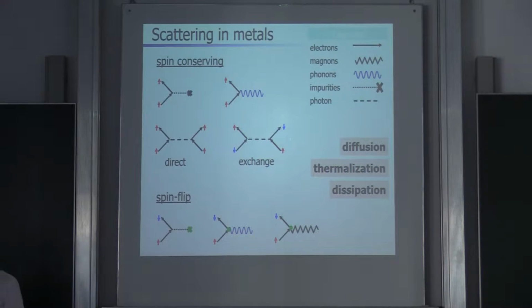So, what's the spin accumulation? Again, we have a diffuse system, that's all we assume. These metals are diffuse systems, and there are all sorts of scattering processes going on. These scattering processes can be classified as being spin conserving or spin flip. Spin conserving processes include scattering at a normal impurity: an up-spin electron hits an impurity and is scattered without losing its spin. These electrons can also scatter at phonons, right? But phonons usually have energy, so while this is elastic scattering, here the energy changes.